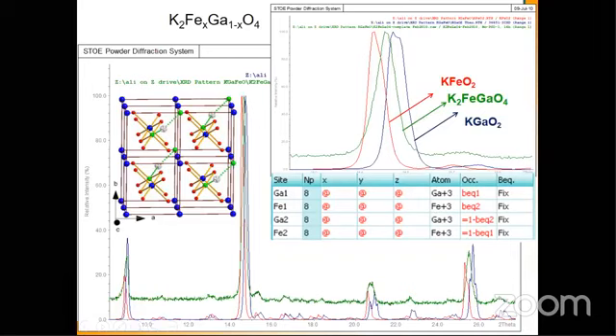I've been using TOPAS and other software for refinement of the diffractogram. So you have to refine the iron and gallium positions in such a way that, if you replace iron with gallium and it is going to be doped 10%, then we have an occupancy of 90% iron and an occupancy of 10% gallium. That has to be the end result of that refinement.